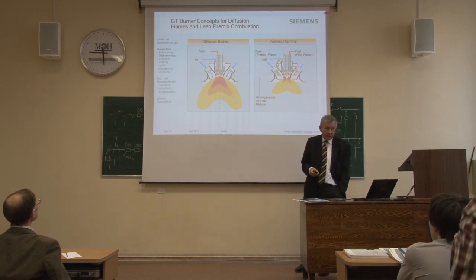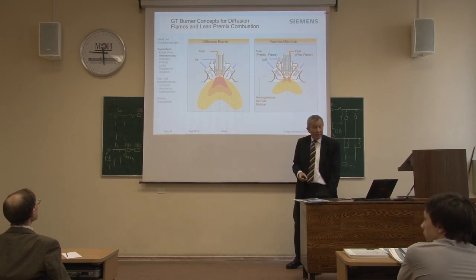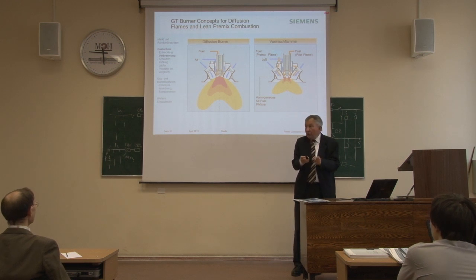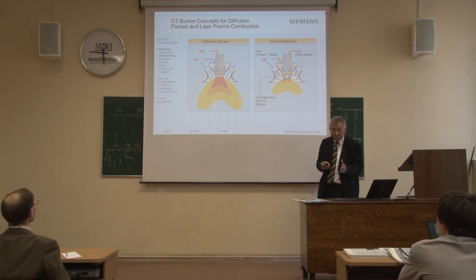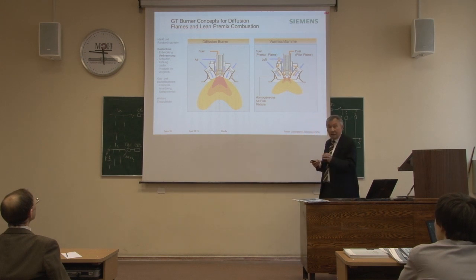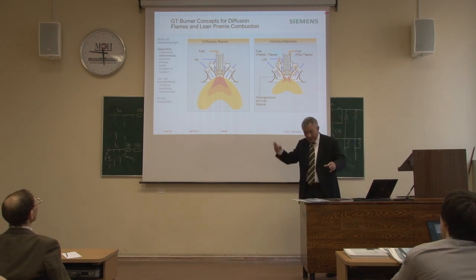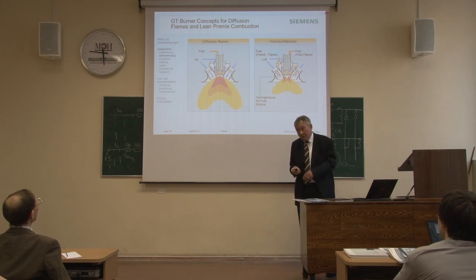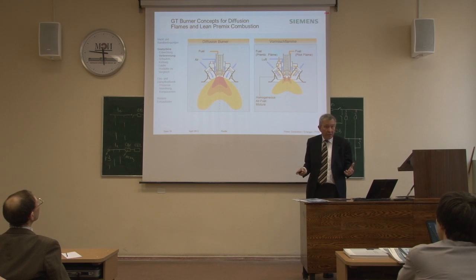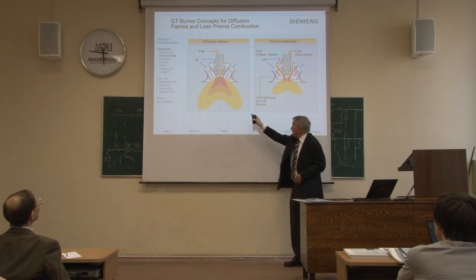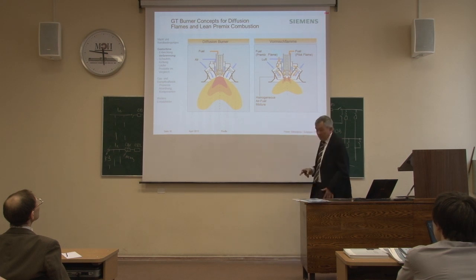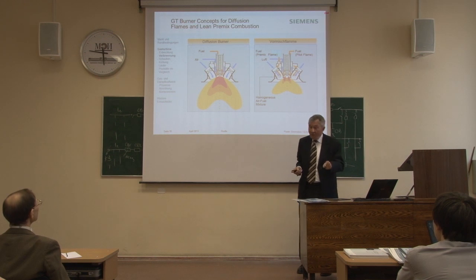And the formation of NOx is proportional to the temperature and the time the molecule stays at that higher temperature. So therefore you want to avoid those high temperatures, and if there have to be some, then let the molecule stay in there as short as possible. And you do this by mixing the fuel and the air beforehand, before it burns, so you get a much leaner mixture, and if this then ignites, then the total temperature is immediately only at that level you want to achieve, and that reddish area disappears, except for a kind of a pilot flame you need to keep the flame going.